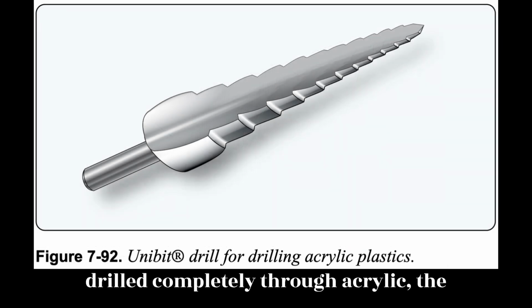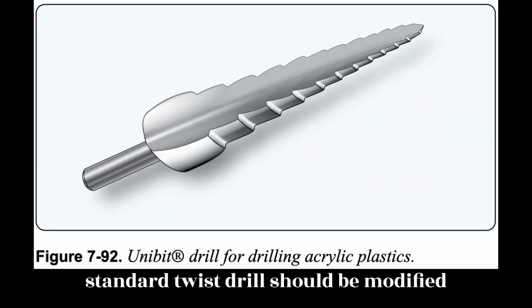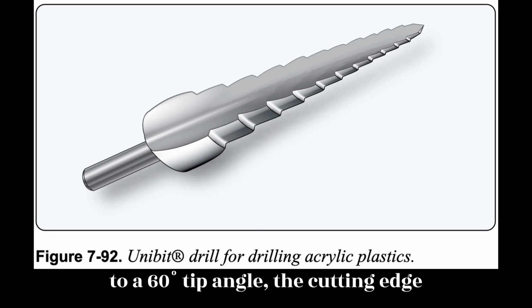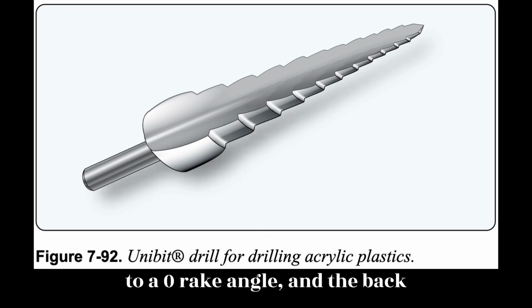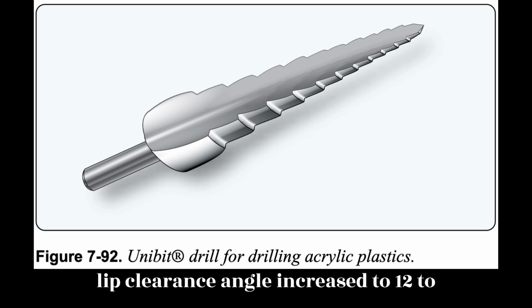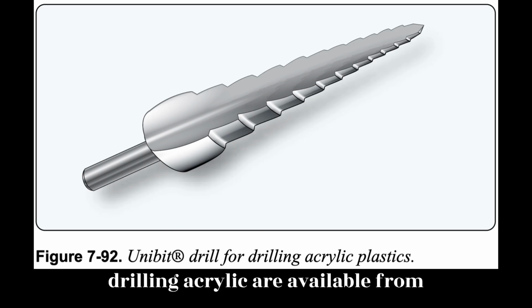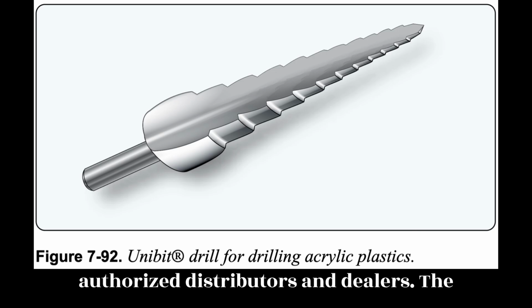Whenever holes are drilled completely through acrylic, the standard twist drill should be modified to a 60 degrees tip angle, the cutting edge to a 0 rake angle, and the back lip clearance angle increased to 12 to 15 degrees. Drills specially modified for drilling acrylic are available from authorized distributors and dealers.